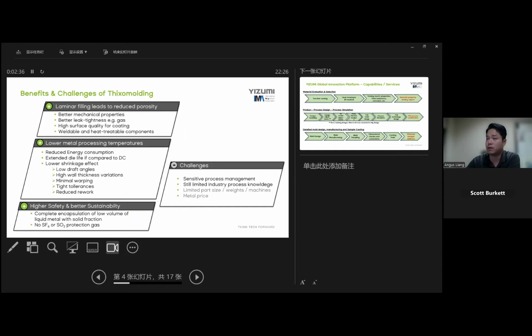And I would like to talk a bit more about the benefits and challenges of Thixomolding, since a lot of presenters have already shown how the process works. We have found this process has laminar filling, which leads to reduced porosities. Because of this, we're able to have better mechanical properties and better leak tightness, for example if you are using these parts for gas. We also have higher surface quality for coating, and the parts are weldable and heat treatable because you have very little porosity. And we also have a lower metal processing temperature, which reduces our energy consumption.